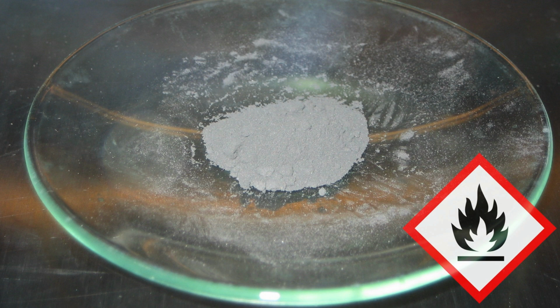The initial alloy composition is important because the quenching process produces a number of different NiAl phases that have different leaching properties. This may result in markedly different porosities in the end product. The most common starting alloy in industry contains an equal amount per weight of nickel and aluminum. Incidentally, the same ratio Murray Raney used in his discovery of the Raney nickel.